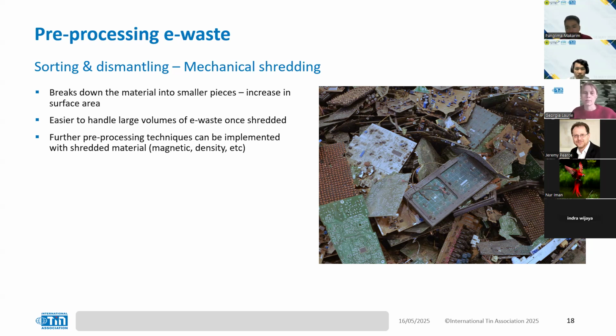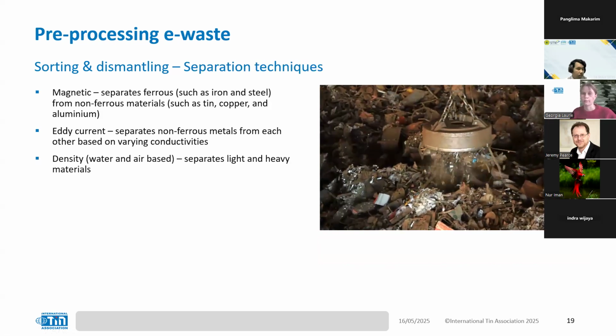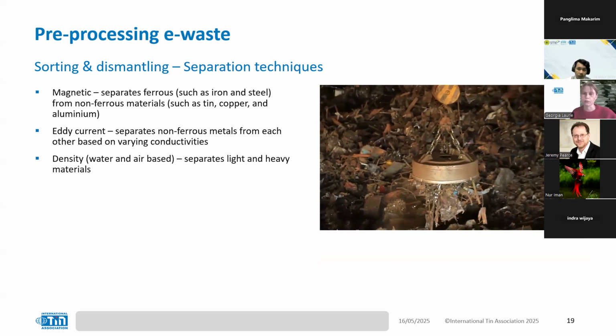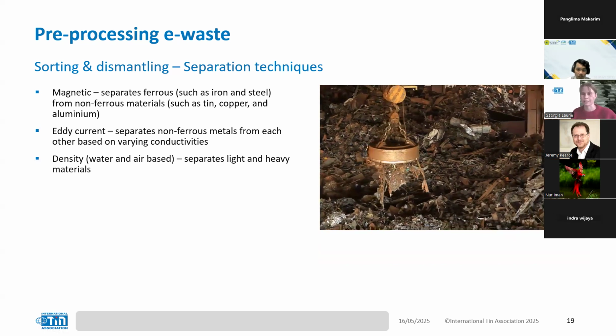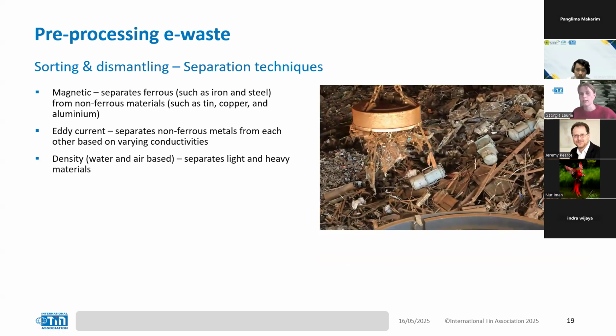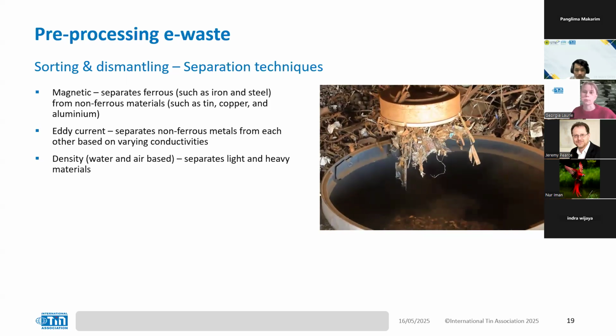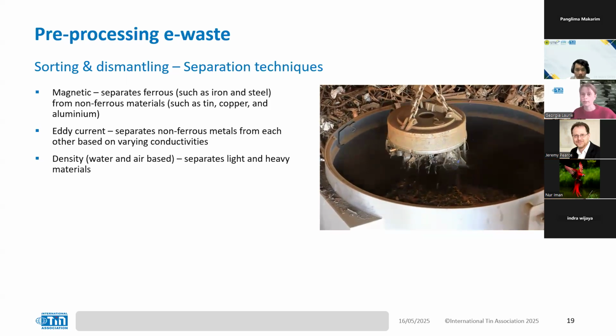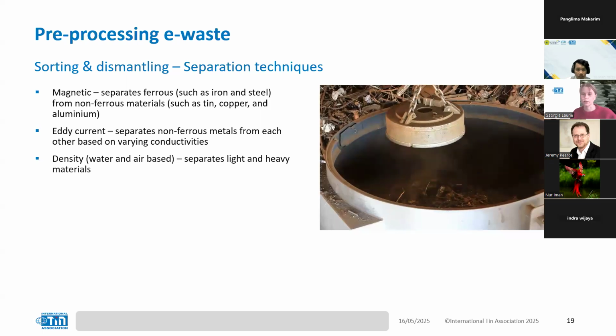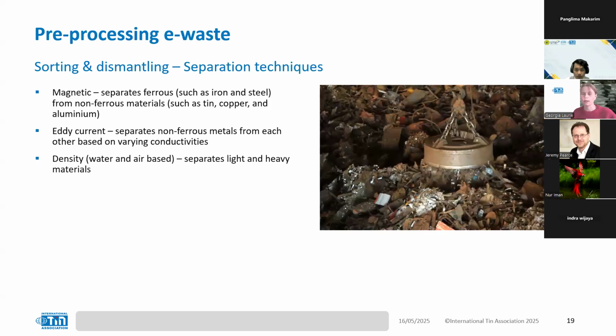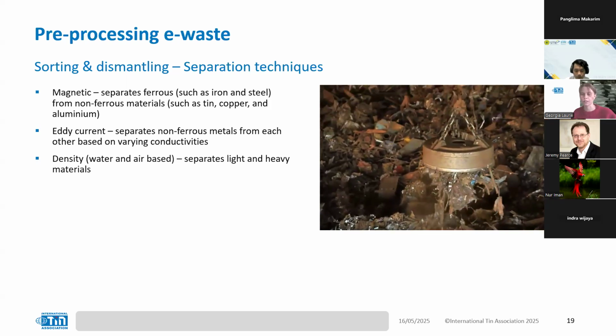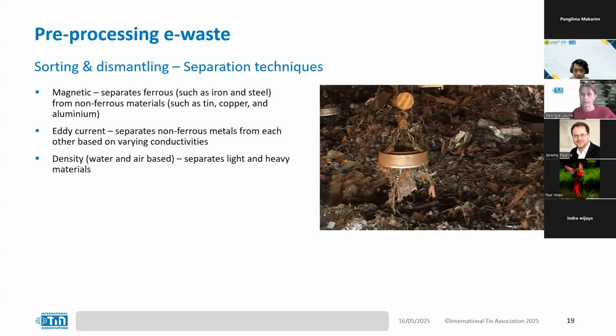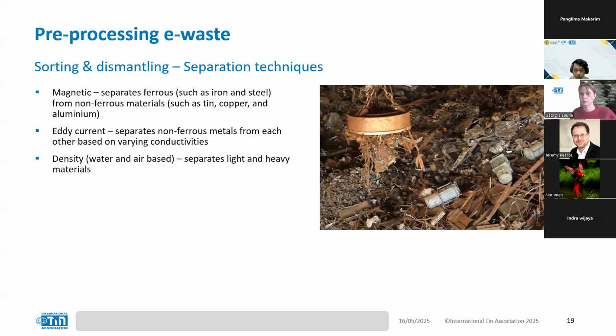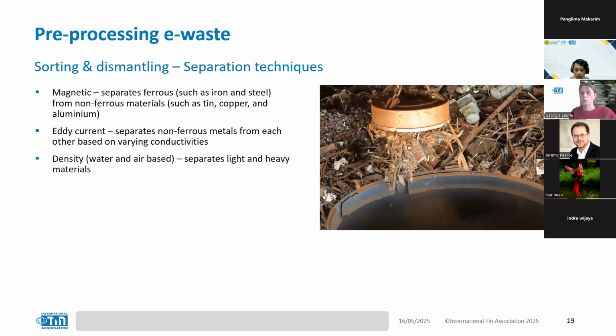This is also good because shredded material enables further pre-processing techniques to be employed, such as magnetic, eddy current, and density separation. Magnetic separation is self-explanatory in that it separates magnetic ferrous metals such as iron and steel from non-magnetic, non-ferrous metals such as tin, copper, aluminium. Eddy current separation separates non-ferrous metals from each other based on varying conductivities. So in some cases, we can separate tin from aluminium, for example. And then we also have density separation. This separates components based on weight, either in an air or water-based environment.